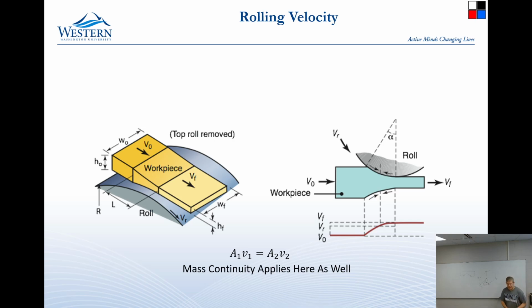So one of the things is, by the constancy of volume, if I have a certain volume of material coming in at a certain rate, the same volume of material has to go out the other side at the same rate. But if it's coming in thick and it's going out thin, and the friction keeps it from getting wider, so it's getting thinner and longer, that means that when it exits, it has to be going faster, because I have to get rid of the same amount of material, but it's thinner. And so what happens in rolling is that the material comes in at one speed, it leaves at a different speed,